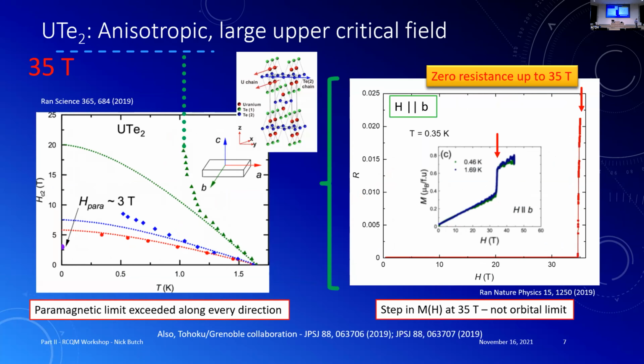I have this clicker. Okay, so when did we know that we had something a bit bizarre, even for a uranium compound? It's when we started actually looking in detail at the upper critical field, which is plotted here on the left for the different directions. So A and C, large, but maybe can at least be acceptable. The B axis, when you get to, let's say, 10 Tesla, and it stops moving, you say, there's something wrong with my magnet or my fridge. But at least in this sample, as best we can tell, this is an almost vertical HC curve, okay?